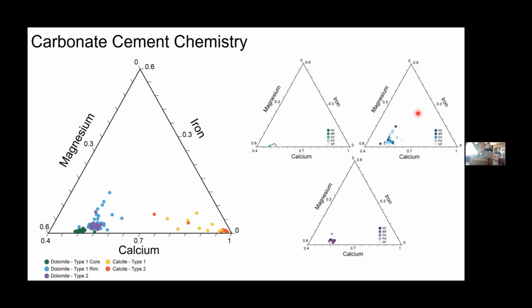Looking now to the rims and the cores, you see a much different story. So these light colors all seem to plot near the bottom of the iron line, suggesting they don't have a lot of iron within the crystal structure. As we move to the more distal locations, we see progressively more iron. And again, if you remember from earlier, that's where we have thicker, more organic rich units that also have higher clay contents. And lastly, we see a similar thing with the type 2 dolomite rims as well, where we see the proximal outcrops have the lowest abundance of iron, and they become progressively more iron rich as we move to the more distal parts of the basin.